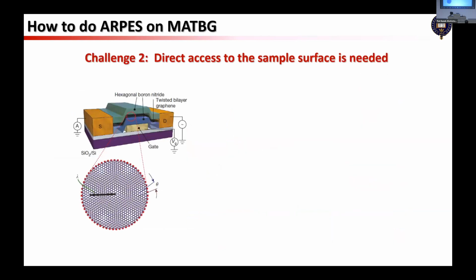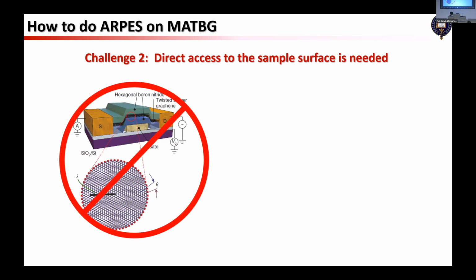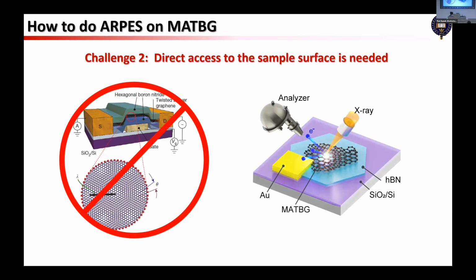But there comes a second challenge. When we survey the devices we want to study, we find that they are typically capped, and they have a bottom gate and also a top gate to tune the carrier density. This is bad news for us, because for photoemission spectroscopy, we shine the light onto the sample, and then we need the electrons to come out so that we can collect them and analyze the energy and momentum. This geometry doesn't work for us, unfortunately. So what we need is to keep the back gate, but get rid of the top gate, so that the light can get access to the sample and the electrons can get out. After the hard work of the whole community for the past maybe 10 years, we were finally able to achieve this goal.